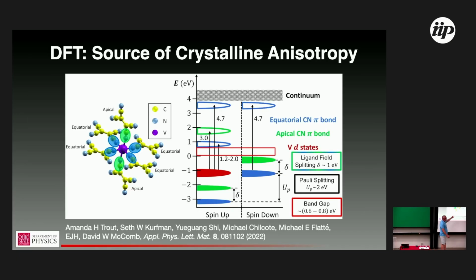This is sort of the cartoon representation of some very nice DFT work coming out of Michael's group that's supported by electron energy loss measurements done in a TEM, validating the electronic structure. And I talked a lot about how the various levels work on Monday, but here I just want to focus on the symmetry. What this DFT model identifies is that, if we take a vanadium-centric view of the material, so this is not quite a unit cell, this is bigger than a unit cell, but conceptually I think this is the easiest way to think about it, we look at a vanadium, there are 6 CNs coordinated to each vanadium. 4 of them are identical and in plane, that we've labeled equatorial here. And then 2 point out of the plane, which are labeled apical.